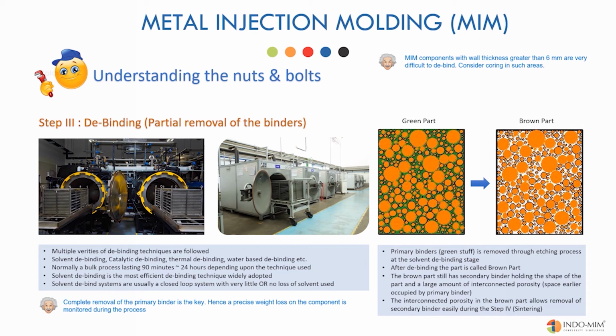As you can see, the green stuff inside the green part is all gone after debinding. The part at this stage is called brown part. The weight loss on the components is closely monitored during the debinding process. The entire process is done in an automated closed-loop system. The solvent used in the extraction process is regenerated. Debinding cycle times depend on the wall thickness of the parts. Thick-walled components take longer to debind. Components with wall thickness greater than 6 millimeters are difficult to debind.